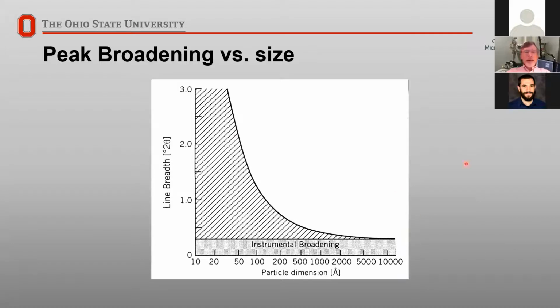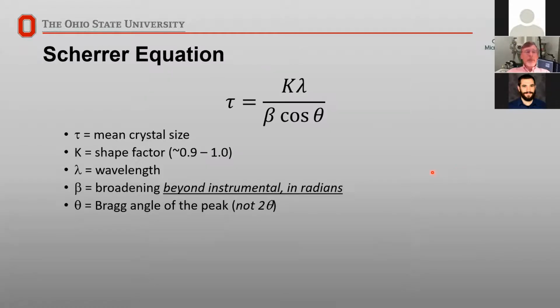Now, actually, the simplest way to do this is to use the Scherrer Equation, which again is a very simple way of going about it. There are more sophisticated curve fitting techniques. But this gives actually very good results. So once again, we have the wavelength of our radiation, which we know are X-rays. We know the angle of the peak. We can measure how much broader the peak is than our instrument. We need to have some sort of a standard. And then we can just very easily calculate the size of the crystal.